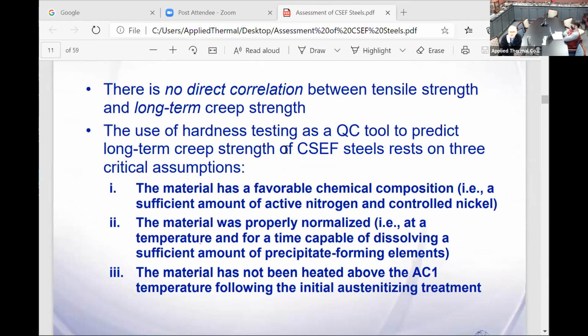The use of hardness testing as a QC tool to predict long-term creep strength rests on 3 critical assumptions. Obviously the composition: the material has a favorable chemical composition, the material is properly normalized, and the material has not been heat treated above the AC1 temperature. So remember those, because that's really what drives why typical condition assessment tools may not give you an adequate idea of the condition of the material.